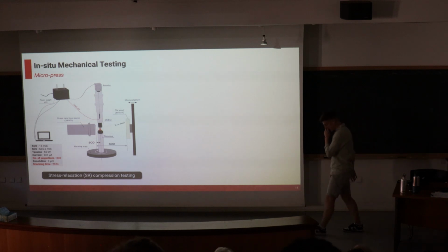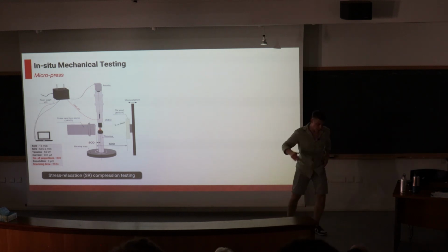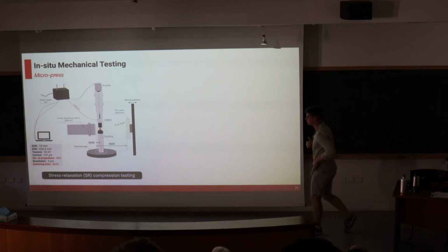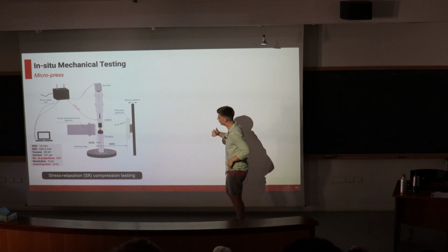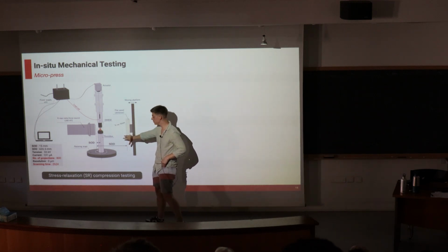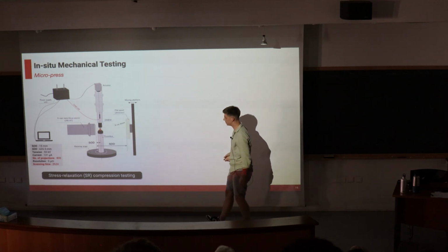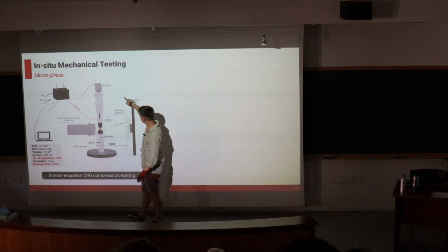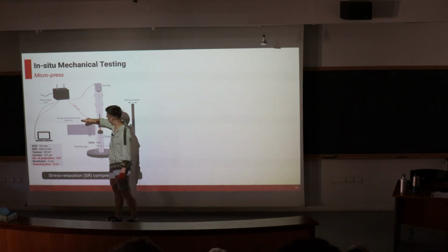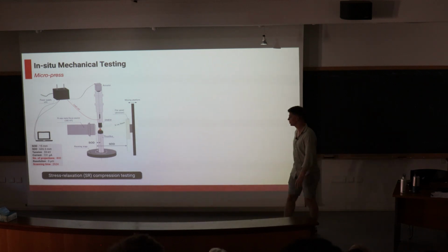Then a little bit more about biomechanics. We really wanted to understand both microstructure deformation and the mechanical properties. To do this, we built a compression setup that will be placed inside the micro CT, in order to have, as I said, the deformation and the mechanical properties. Basically, it's an actuator linked to a 3D printed rod with a load cell, and with the computer we can apply different ranges of compression.